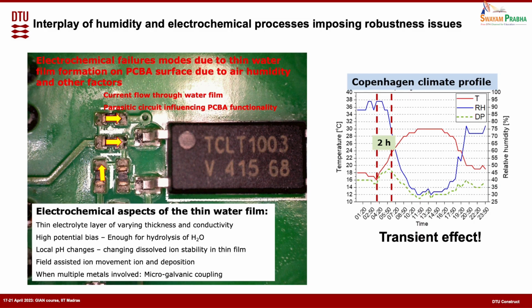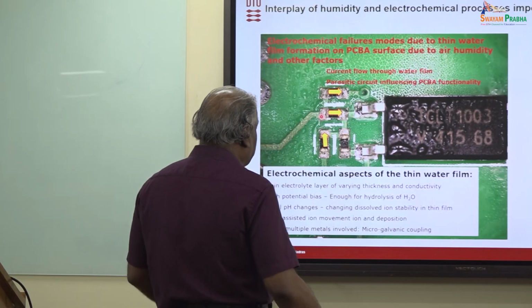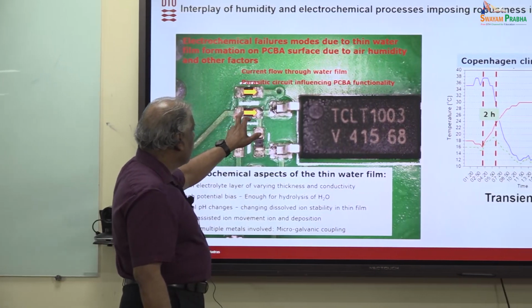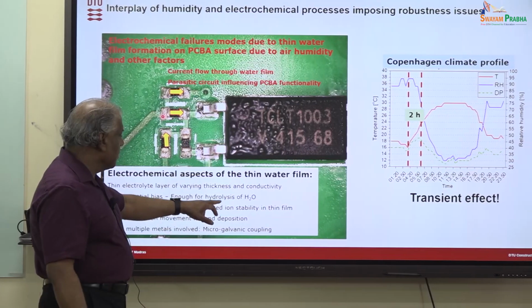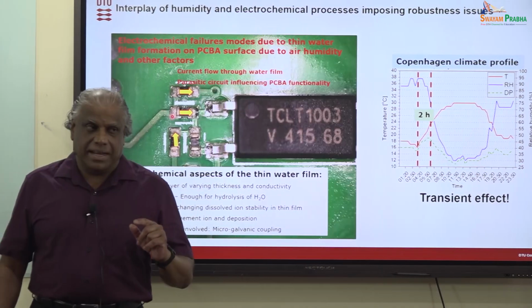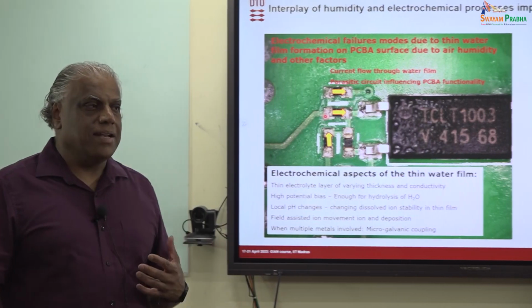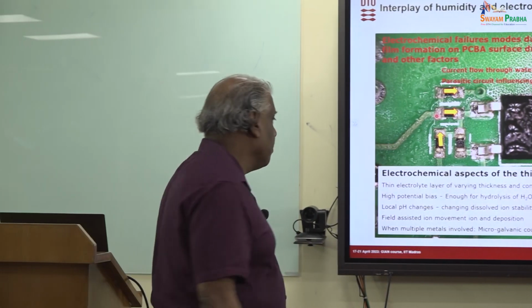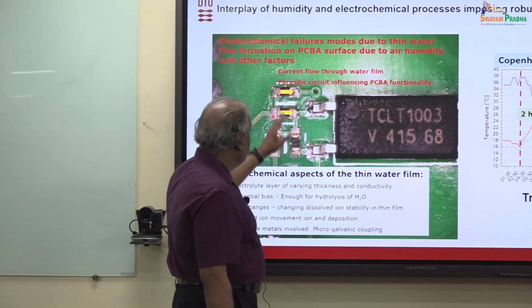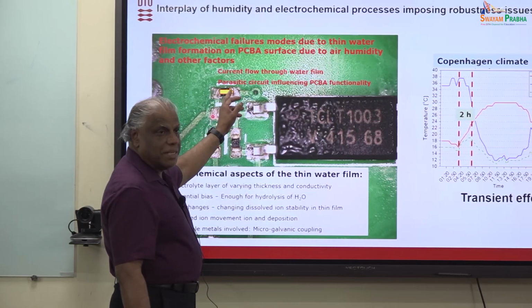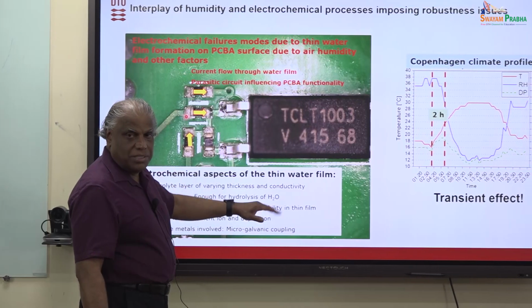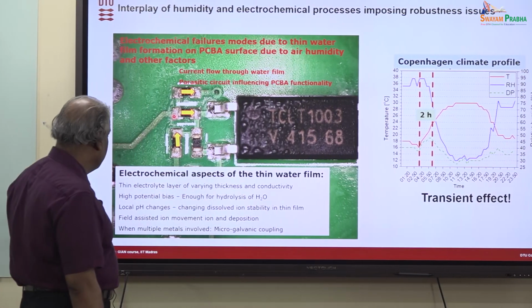Because when you have hydrolysis of water producing so much on both electrodes, that means that on one side of the electrode you reduce the pH, and on the other side you increase the pH. You have a very sharp change in the local pH on both sides of the electrode because of the hydrolysis of water. And you will see that later, when you have an experiment, at least 50% of the current is used for hydrolysis of the water, and 50% of the current is only used for the metal dissolution. So that means that there is a lot of hydrolysis of water which produces a lot of this pH change.